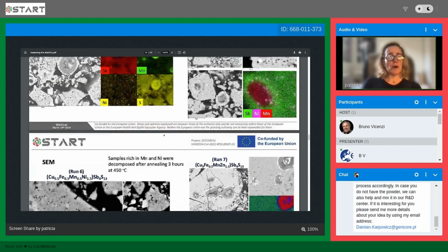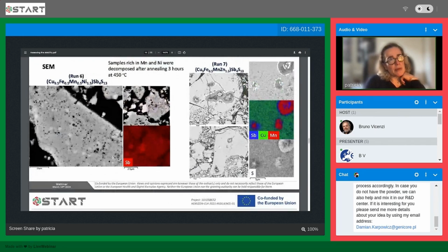And one of the points that was really important, and we are investigating now, is the fact that all samples after annealing had this type of dark phase. It looked like pores, but we were not completely sure what it was. Now we know what they are. This is a very important aspect for tetrahedrite, because no matter what the composition is, if you have tetrahedrite after annealing, in our case, so the materials produced by ball milling, you always get this dark phase.